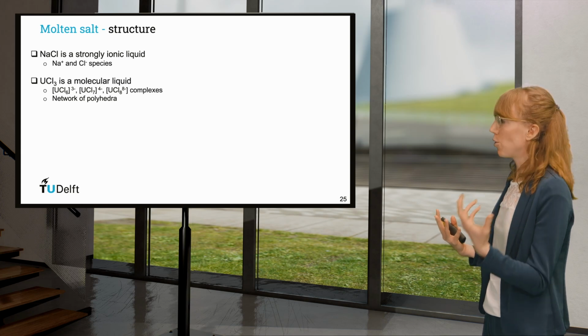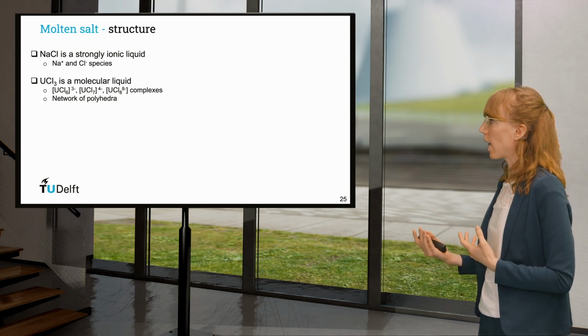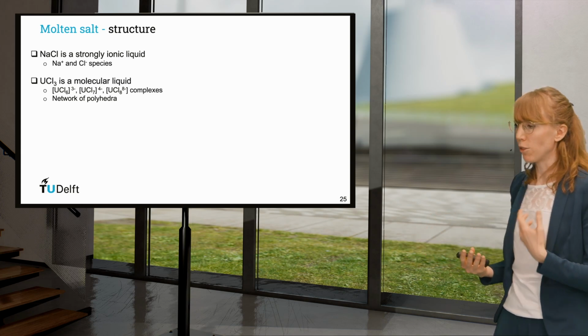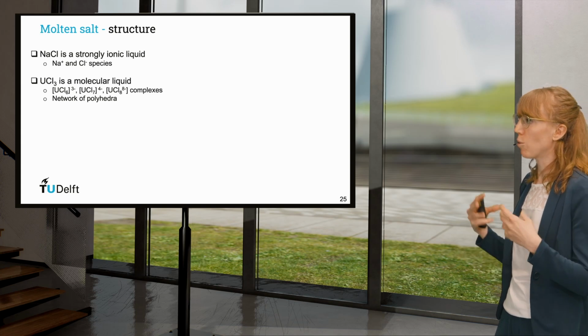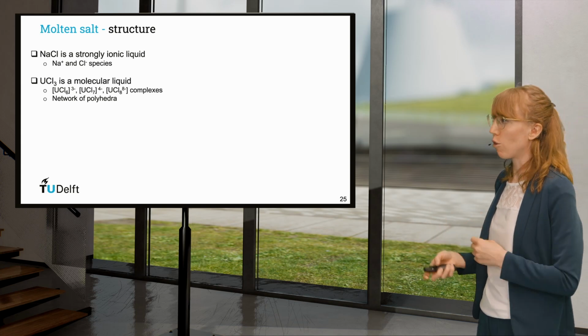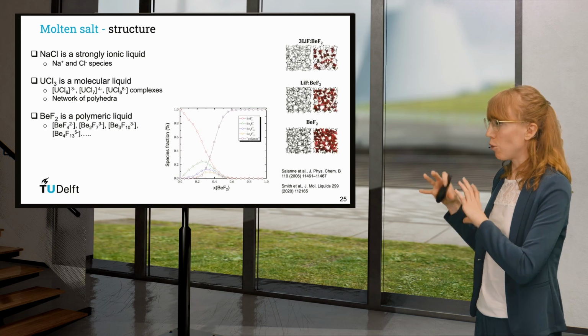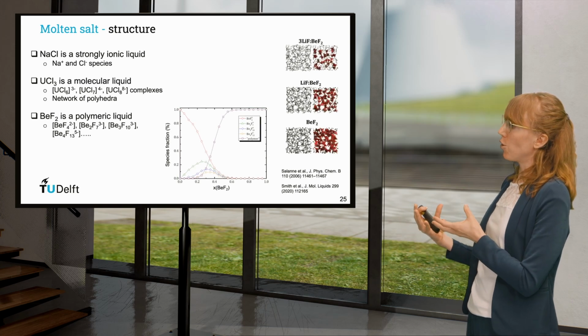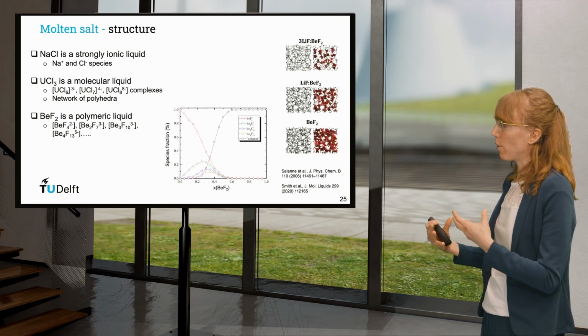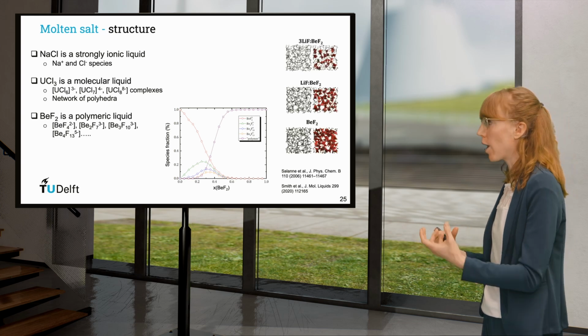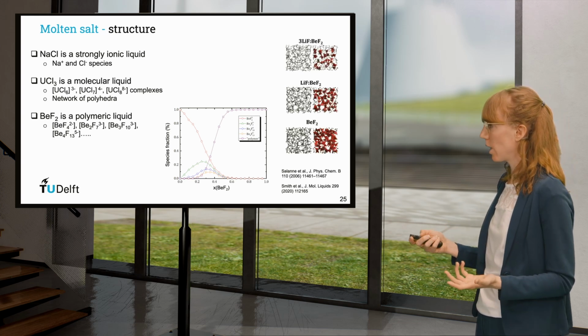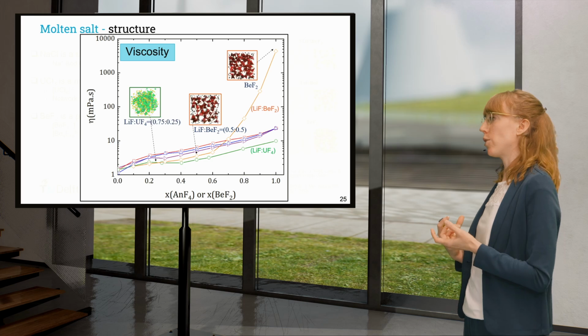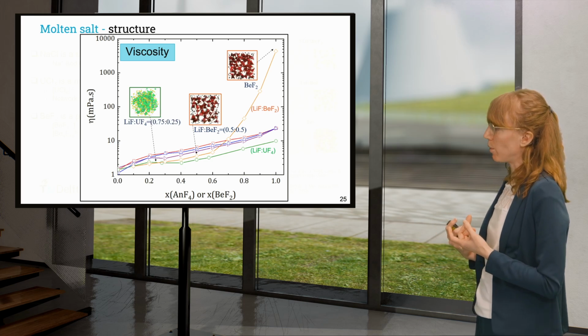It is basically sodium cations and chlorine anions. But if we add uranium to it, we start to form complexes and a network of polyhedra. In a mixture with beryllium fluoride, you get a polymeric liquid where you form even dimers, trimers, and eventually polymers. This has a direct consequence on the microscopic properties.